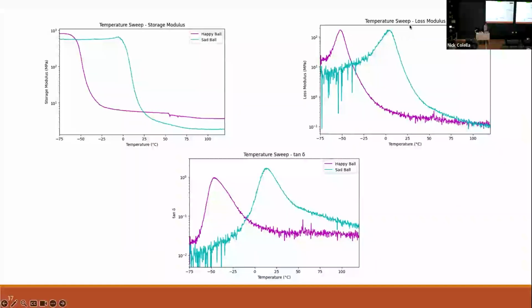We can also look at the loss modulus, and we see a peak in the loss modulus right around, again, the same temperature, that glass transition temperature. We see a peak in the loss modulus for the happy ball, again, at its glass transition temperature. Finally, we can look at the ratio between the two, the tangent of delta, and this is basically how lossy it is relative to elastic. And we see a peak, again, negative 50-ish for the happy ball, and right around room temperature for the sad ball. So this is why the sad ball does not bounce.